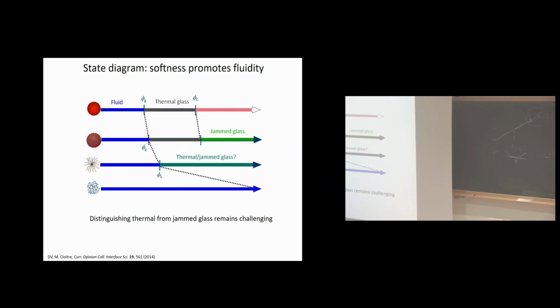And so then you have the microgel, which is somehow in between. Okay, there is a glass transition, almost at the same volume fraction, but this depends on a number of parameters, as I have indicated. You have all this regime, but then there is a second transition to what we call jammed glass. And I think this is an interesting analogy to granular material. So thermal glass means that my constrained particle still does Brownian motion. So then kT is basically responsible for the properties. Jammed glass is what I already showed, is contact. So basically, there is no longer kT in this respect. I have really frustration and deformation and elastic contacts, basically, that are important.